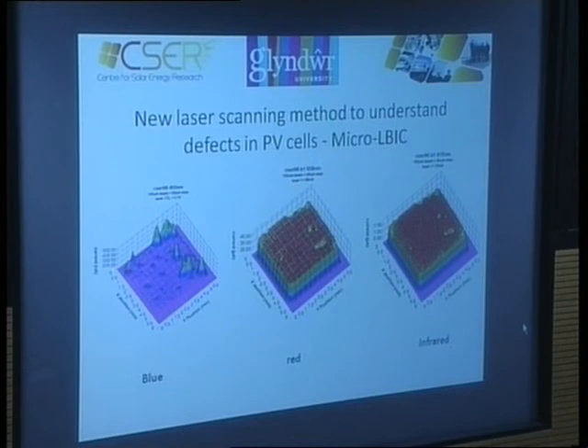And you might wonder, well, what effect does that have? Because it's letting a bit of the blue light through, isn't that good? Because that's one of the problems with cadmium telluride cells. They're not very good in the blue. Well, you can see that in exactly those regions, in the red and the infrared, where the light does get through to the cadmium telluride, the performance is poor. So this really tells you that it's no good just saying, I've managed to make a really good piece of material and get a good device on it, because this now has got to be manufactured on a large scale. And so you can see the challenges. Materials uniformity is everything.